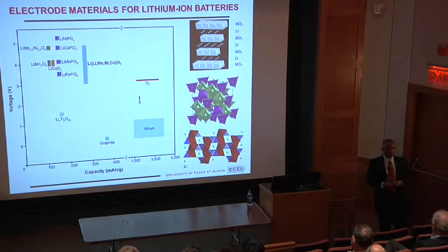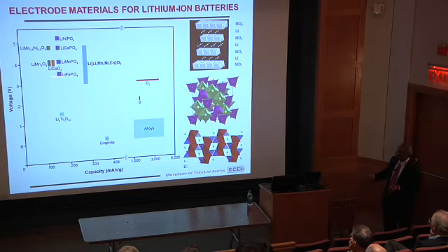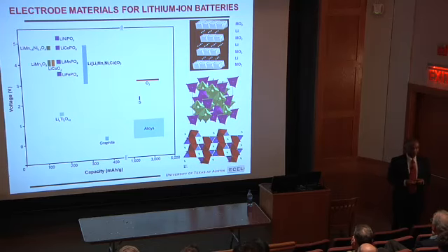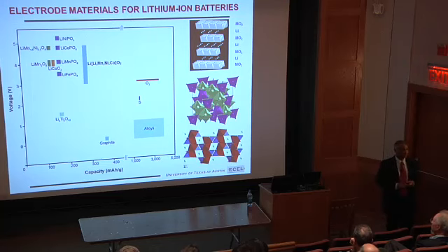I think I may not be able to go through each one of those. But anyway, that's what we work on. You look at here, all these materials have capacity in terms of hundreds, less than 300, or practically, right now, less than 200 milliampere hour per gram. Sulfur has 1675 milliampere hour per gram. Oxygen has double of that if you get lithium oxide Li2O, 4 electron transfer per oxygen molecule. So it's a huge amount of energy or charge you can store here.